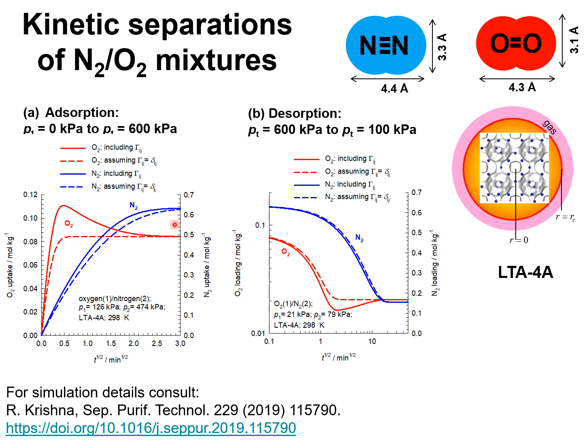The equilibrated sample is then exposed to an environment at a total pressure of 100 kilopascals, 21 kilopascal partial pressure of oxygen, 79 kilopascal partial pressure of nitrogen. The transient desorption kinetics are simulated using models in which,